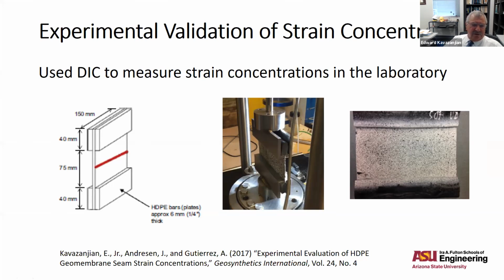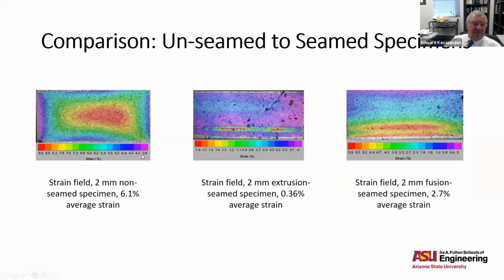We modified our triaxial device so that after welding bars on the top and bottom of a geomembrane coupon, we could load them in some grips on the triaxial device and load it in tension. Here is the geomembrane loaded in tension. And we speckled the geomembrane with white paint so we could use digital image correlation to measure the strains in the geomembrane as we stretched it. So here are some results.